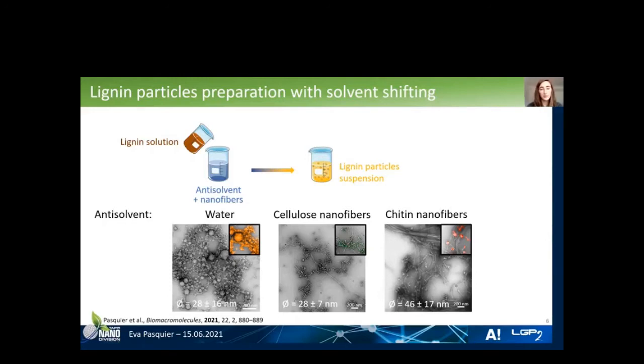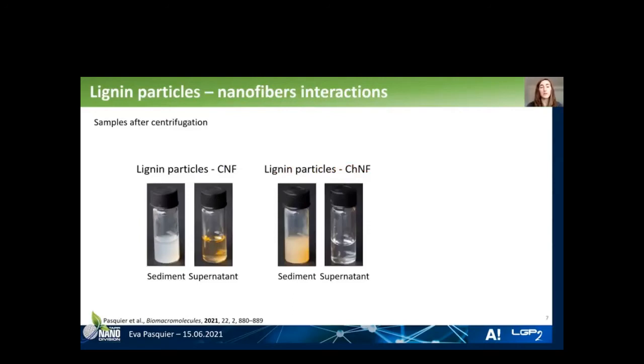For example, here with the cellulose nanofibers, you can see that the particles are way smaller, however they are still aggregated. And when we added some chitin nanofibers, you can see here, the lignin particles are actually well dispersed on the nanofibers. So we have adhesion, and we wanted to look at the interaction between these. So for that we did some high-speed centrifugation of the suspension. So the lignin particles with CNF and the lignin particles with...